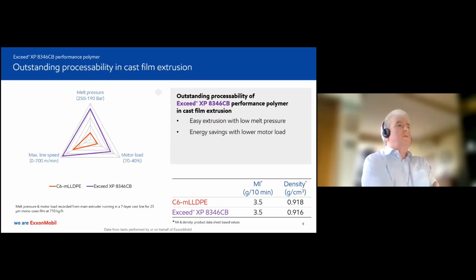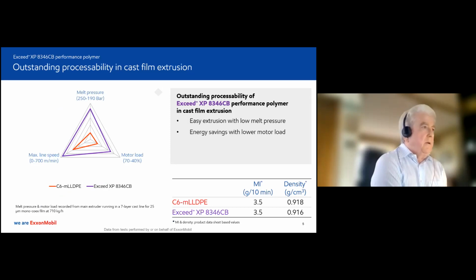Now, in addition to those attributes, it actually processes very well in the extruder. So you can see here that, compared to this conventional C6 metallocene, the melt pressure is significantly lower, the motor load is lower, and the potential to run at a higher line speed is there. So that's all good. So what that means is that, from a sustainability point of view, we can look at potential energy savings here. And as you're about to see, we're able to introduce some interesting properties too, which would mean that customers can even consider some down gauging.